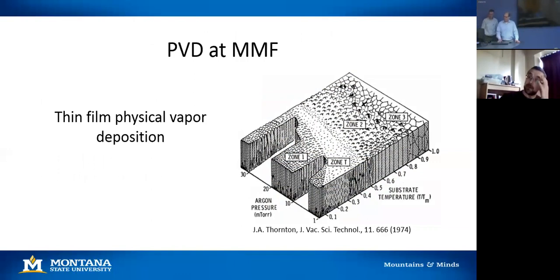So the second section of tools is PVD, physical vapor deposition. This is how we deposit thin films in our facility, both metals and dielectrics. This is, I think, in the thin film community, a well-known diagram by Thornton from 1974, and it was actually done earlier by some other people, with different variations of it. The main point of this is to show that these films, independent of material, have a structure that depends a lot on the process parameters. On this axis is your temperature, where 1.0 is the melting point of the material you're trying to deposit.